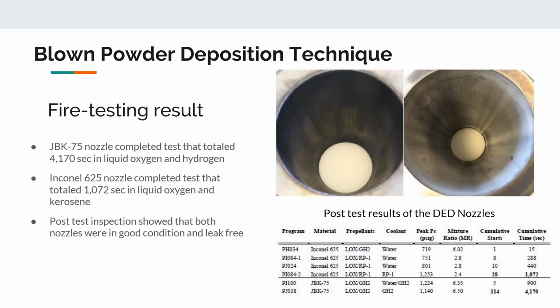The JBK75 nozzle completed hot fire tests that totaled to 4,170 seconds in a liquid oxygen and hydrogen environment, while the Inconel 625 completed hot fire tests that totaled to 1,072 seconds in a liquid oxygen and kerosene environment. The test results, which are summarized in the table, and the inspection of the nozzle after the fire test, which can be seen on the image, showed that both the JBK75 nozzle and the Inconel 625 nozzle were in good condition and leak-free. This successful test shows that blown powder deposition is a feasible technology for the fabrication of channel wall nozzle structures.